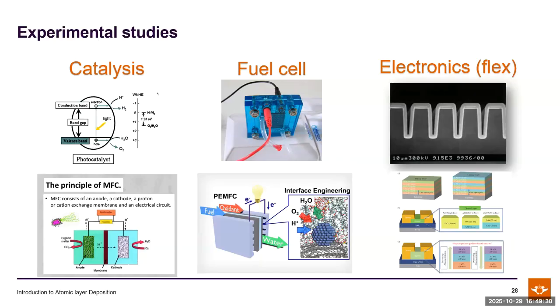Electronics, and you can see that this is one of the major advantages of atomic layer deposition. You can see in this so-called trench, which is the most difficult one for the deposition process. You know that with CVD or PVD, the physical vapor deposition or chemical vapor deposition, when you have this kind of step change, you will have a problem with the trench, the hole, because you are going to block the hole, and then you need to do either an etching process or another process to cut through the hole. So I think those are the nice features that ALD can do.